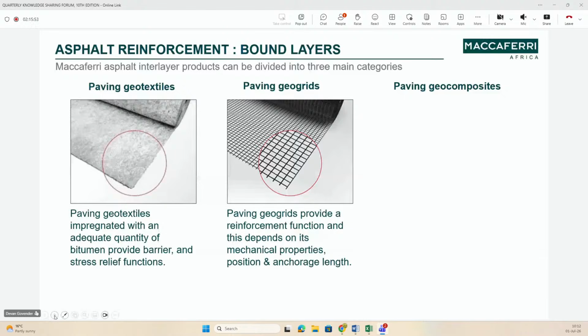Now, in those bound layers, this is where the challenge comes in. So you've got your layer works, but if you've got any cracks, because you're going to have tires moving across the surface all the time, any crack that propagates is going to go into the surface. By introducing a geosynthetic into that layer, what we're doing is we're stopping the crack from propagating onto the surface.